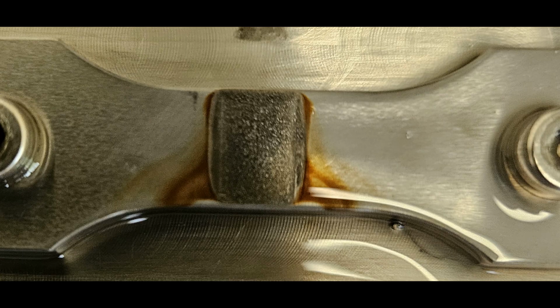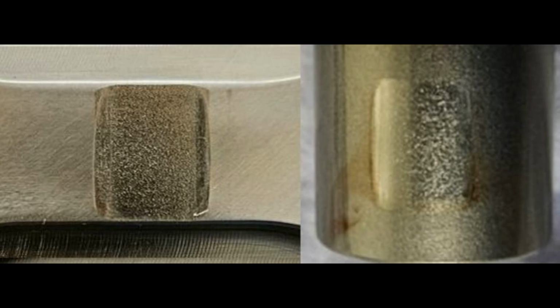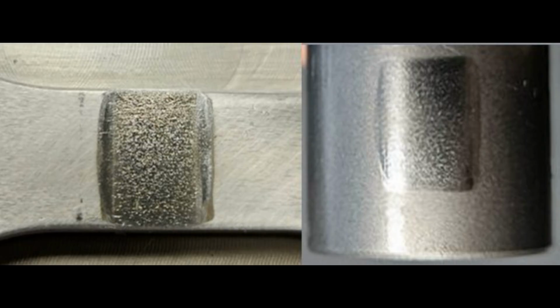This example shows a test run at 4mm amplitude and 10 Hz with PAO4 as the lubricant. The contact pressure was 1 gigapascal. After 600,000 reciprocating cycles, in other words 1.2 million fatigue cycles, the specimen surfaces look like this. After 1.5 million fatigue cycles, they look like this.